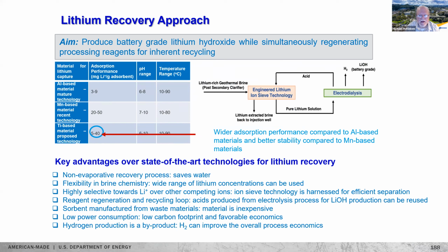Our titanium-based nanoparticle absorbent, which is coated on a diatomaceous earth substrate, has wider absorption performance compared to aluminum-based materials and broader pH and thermal stability compared to manganese-based materials. For the Salton Sea brines, we may refine the substrate and the platform for slightly larger sized absorbent particles. Some other substrate candidates include alumina, alginate beads, or magnetic substrates, which can be separated from the liquids under magnetic fields.